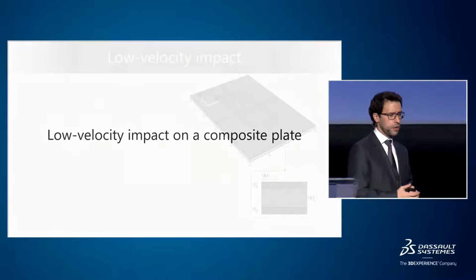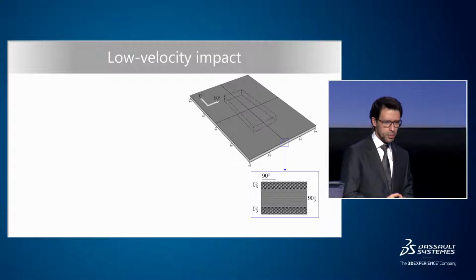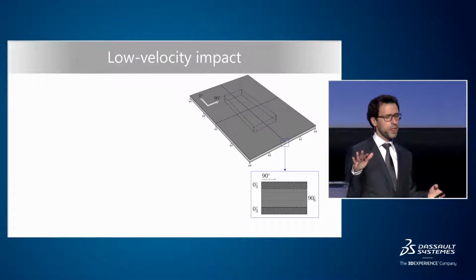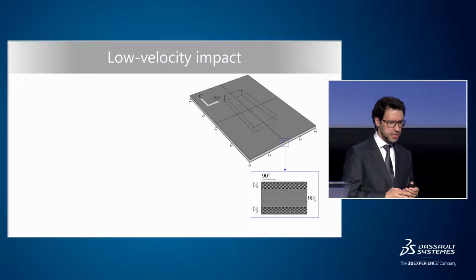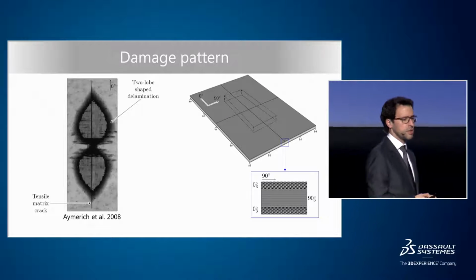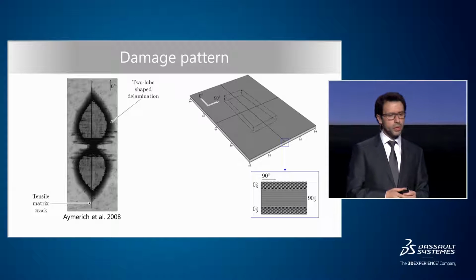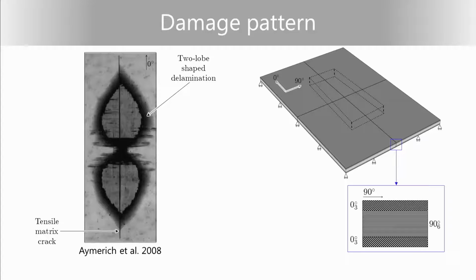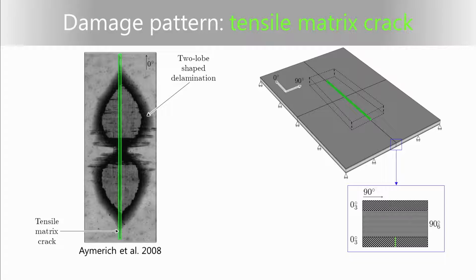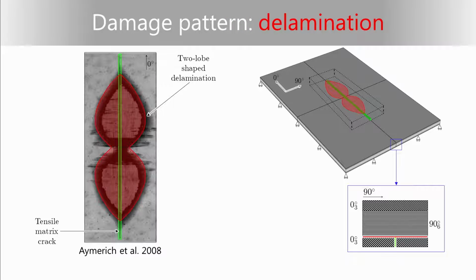Let's look at an application of that, a low velocity impact on a composite plate. This is a plate which has 3 plies, a 0 degree, 90, and 0. It was tested in 2008 by Aymerich et al. And what they observed was that the first thing to fail when there was an impact in the center was the bottom ply, where you'd have a crack shown in green. Then you'd have delamination between the 0 degree bottom ply and the 90 degree middle ply. And this delamination will have this form, this shape shown in red of a peanut.